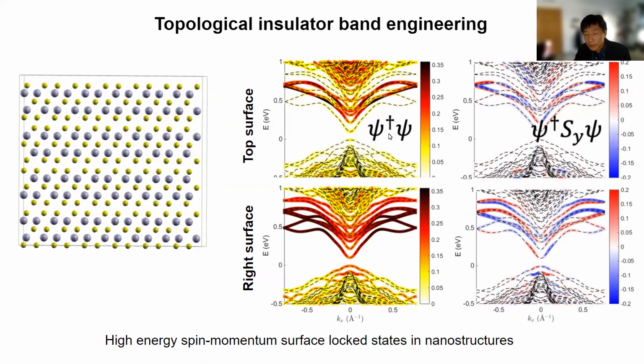And that's the first observation that we see. We also observe that the surface states also occupy the higher energy bands rather than just the first band. And if we look at the spin polarization, we observe a very clear spin momentum locking. If we look at the spin polarization along the positive k direction, we see that it's negative. But if we switch the direction of the momentum, the spin polarization also switches sign.